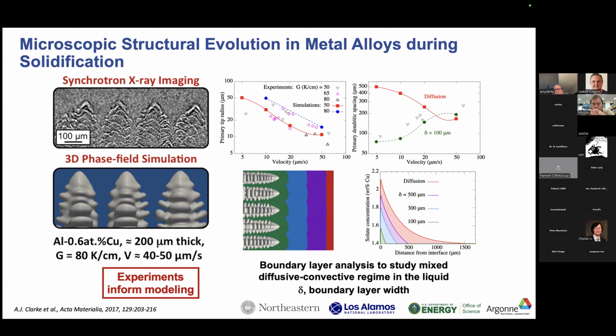So if we think about solidification, we end up building up a solute boundary layer during directional solidification, and we know that we have convection in the melt that impacts that. And so what we did is we actually truncated the solute boundary layer. And when we do that down to about 100 microns or so, now we have good matching with the experiments.